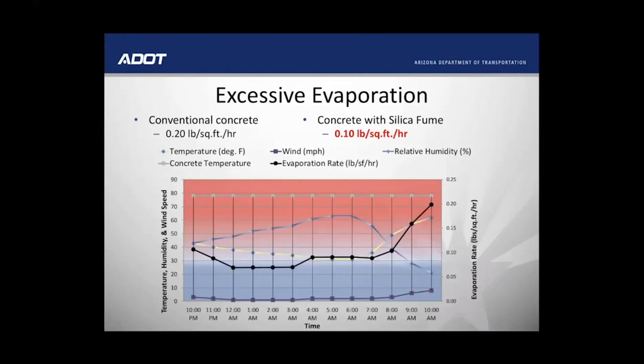With those conditions, the placement of the concrete was delayed until we had more favorable conditions seen here. These were the conditions for the I-40 Belmont Bridge project, which was an accelerated bridge construction project where the new bridge was constructed alongside the old one demolished, and the new one slid into place. With the silica fume bridge, we didn't experience a single crack in the deck.